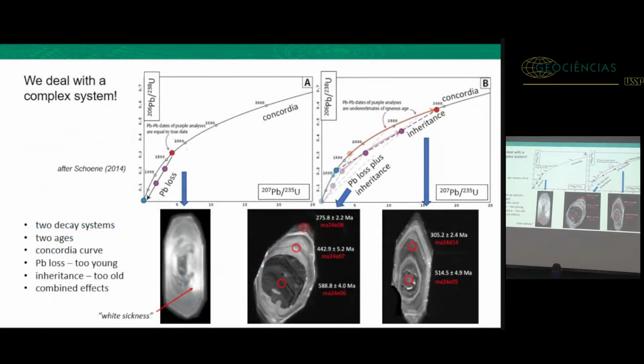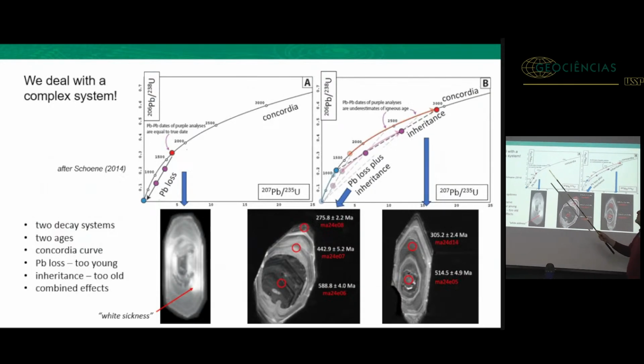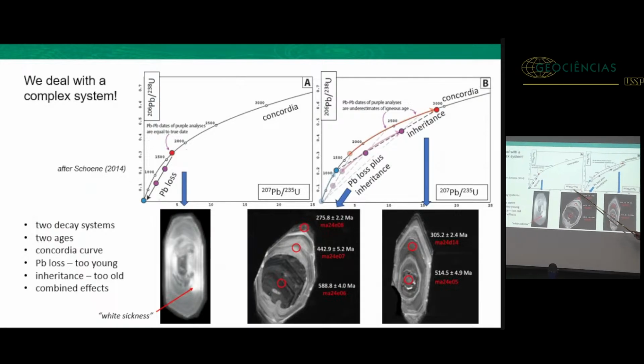So we deal with a complex isotopic system. These are three grains of zircon imaged with cathodoluminescence. This is the famous Concordia diagram. So 206 radiogenic over 238 uranium, 207 radiogenic over 235 uranium. So any zircon where the two ages are identical would lie on this line. And now we have zircons which have lead loss. And when you look carefully at your CL images, you see that many zircons have this fuzzy attitude, and parts of the grains here are white.